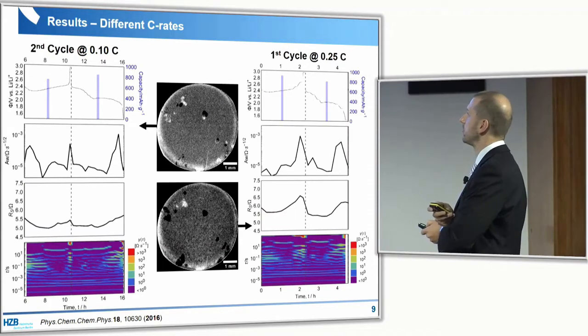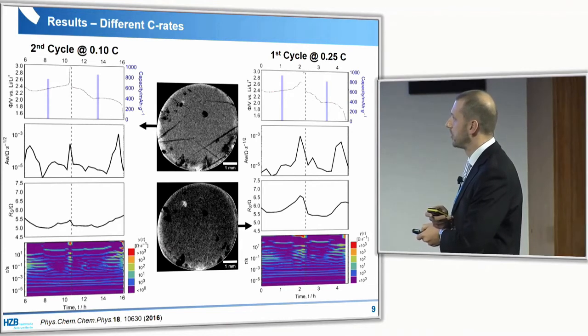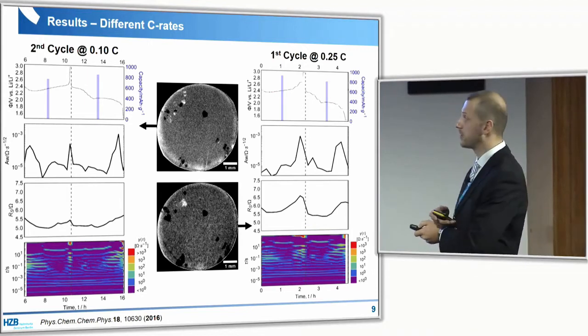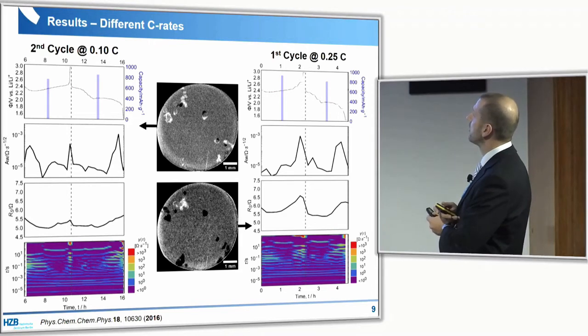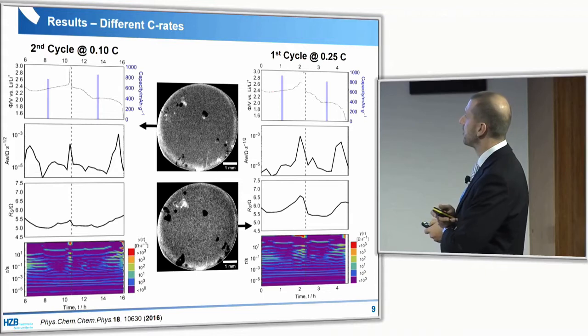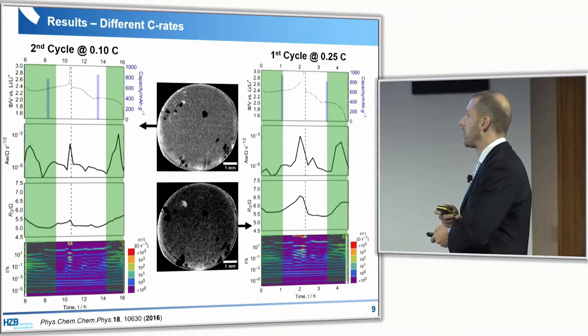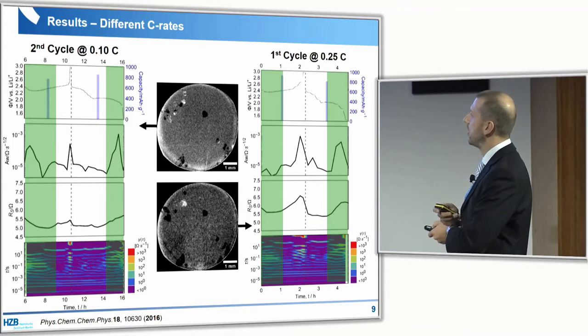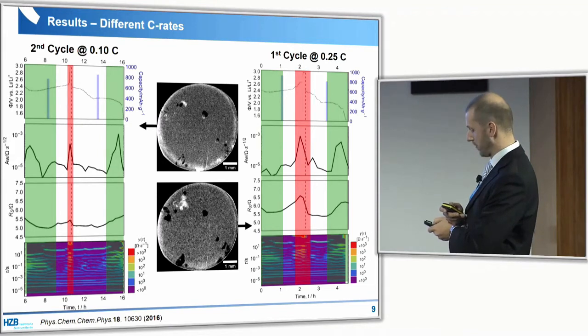Into these two cycles, you can again see a very sharp sulfur charge transfer process, and this correlates very well with the appearance and disappearance of these chunky sulfur dendrites. When you increase the C-rate, you can see this mapping is changing. This relaxation process is related to the Li₂S formation process and the solution precipitation-dissolution process, while this one, which is much more narrow, corresponds to the sulfur charge transfer process.